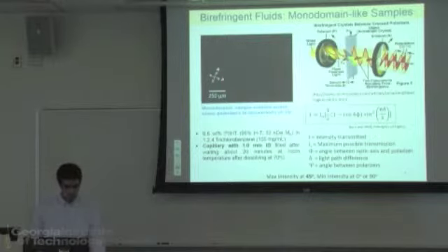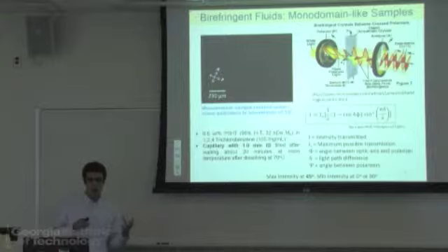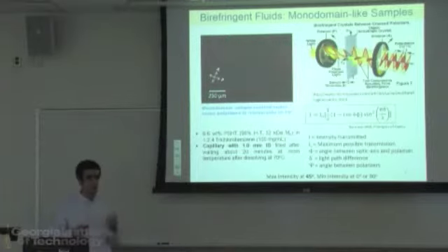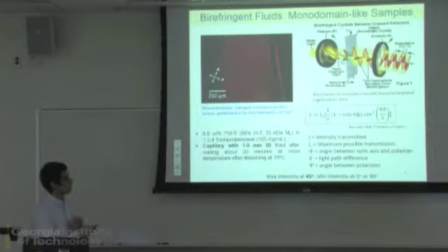One way to characterize this long-range ordering is to use polarized optical microscopy. Here's a schematic where you have two crossed polarizers, and in between you have your sample, which has some anisotropy or some kind of order to it. If it was completely disordered, clearly the light that's polarized in this direction would not pass through the perpendicularly oriented analyzer, so it would just be black on the other side. But if you do have an ordered material, due to the two different refractive indices, you will have a bright image that appears through this analyzer.